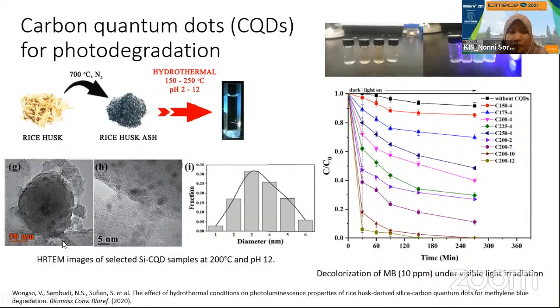Okay, right. Then we tried to degrade the methylene blue. We tried the decolorization of the methylene blue at around 10 ppm under visible light radiation by using these quantum dots synthesized from the rice husk. Okay, so the best performance that we can get is after more than 4.5 hours, we can almost fully degrade around 10 ppm of the methylene blue.